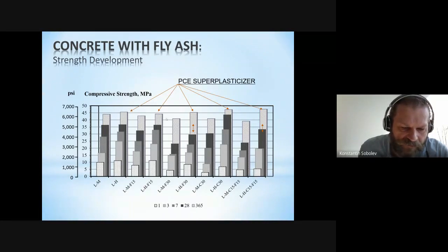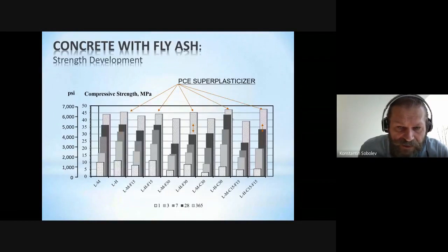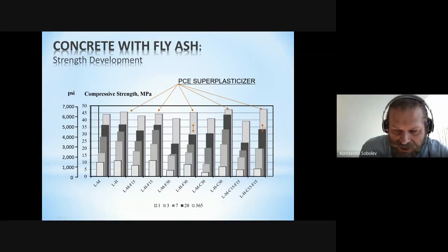Obviously, if we look deeper at different types of fly ash, you can see that strength development can be really boosted with the use of polycarboxylate superplasticizer. Obviously, we can see that the Class C fly ash was outperforming Class F fly ash, and even in a 15% combination of Class C and Class F fly ash, we still had relatively good performance, reaching the performance of reference Portland cement concrete. Especially at 1 year, we didn't see a difference between these types of concrete. So again, up to 30% of Class C fly ash and 15% of Class C and Class F can be used when we use fly ash in combination with polycarboxylate superplasticizer.